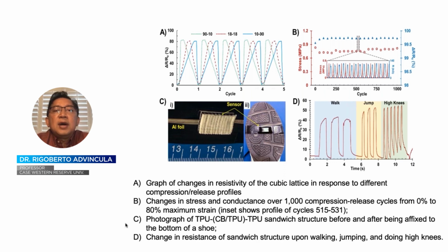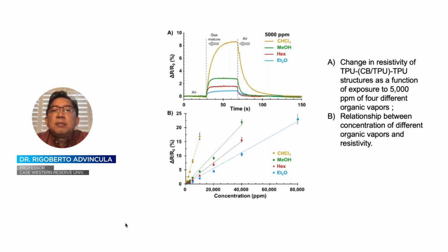And moreover, we can determine the right percolation threshold as well as the cyclic representation, reproducibility of that response. Moreover, what's interesting is that these materials also have a gas sensing capability. So in this case, it can differentiate between chloroform, methanol, hexane, although we have not done a lot of figures of merit yet, it showed a concentration response and a slope change depending on vapor that was present.